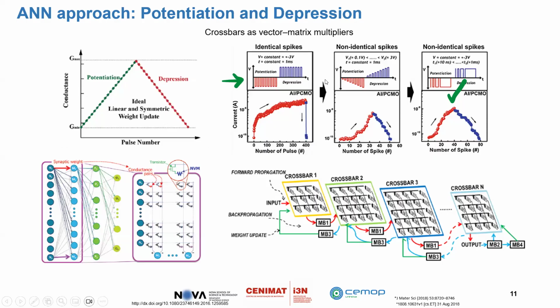So people tried, for example, I have some examples here for you. If you have identical spikes, which is ideal because you can do training, you can actually work with this device. On this specific device in the literature, they showed potentiation with this trend of increase and then suddenly abrupt depression. So it's not actually very ideal. So they changed to non-identical spikes, like increasing the amplitude of the spikes, and then finally they reached this linear and symmetric weight update by changing just the pulse width, which is the last scenario.